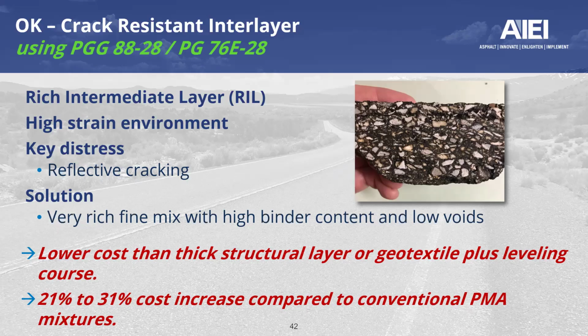I appreciate the information. Maybe the only thing to add on Oklahoma, if we go back to the history: the first section on the NCAT test track, the base layer employed an Oklahoma mix, and that emulated the rich intermediate layer that Oklahoma was very pleased with the performance. And then the year after, they decided to pave about, I believe, 2 miles on I-40 using the rich intermediate layer, and they've seen fantastic performance until now. And then we've also taken a look at the tonnage and the frequent use of such mix for the state of Oklahoma. Good. It's interesting to see how the performance in the UK and Oklahoma model each other, and it's very good.